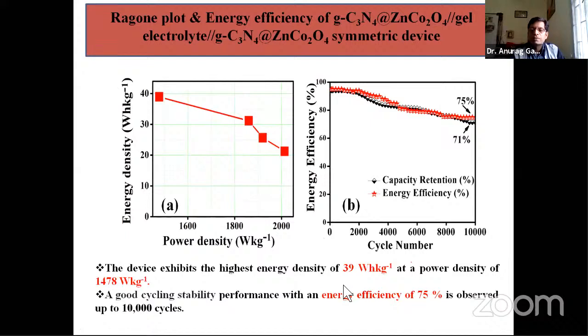So the energy density for this device is 39 watt-hour per kilogram. This is very good from the point of view of capacitors. The power density is 1478 watt per kilogram. This is a very good value, and there is a quite significant enhancement in the energy density by adopting this strategy of making the composite of graphitic carbon nitride and zinc cobalt oxide. The cycling performance is also good. We have tested up to 10,000 cycles, and 75% efficiency is retained.